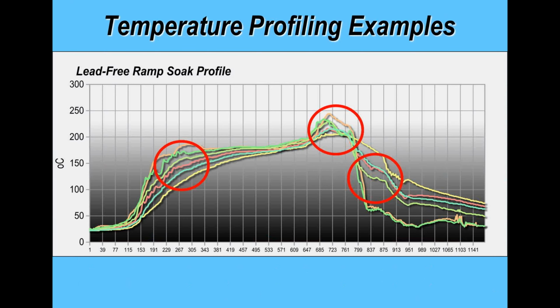So if we go back to the profile, what's profiling all about? Well, fundamentally we're measuring the temperatures, and what we want to measure is the temperature differential across the printed circuit board and on different terminations. What we're trying to do is find out what's happening to the board and components as it goes through the reflow soldering process. And here you can see variations in temperatures in the places that you probably would expect, actually.